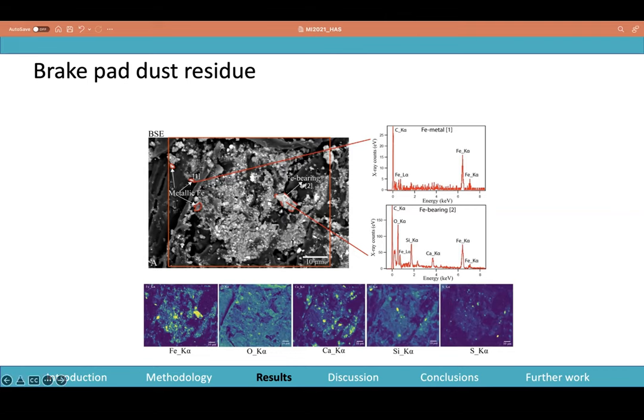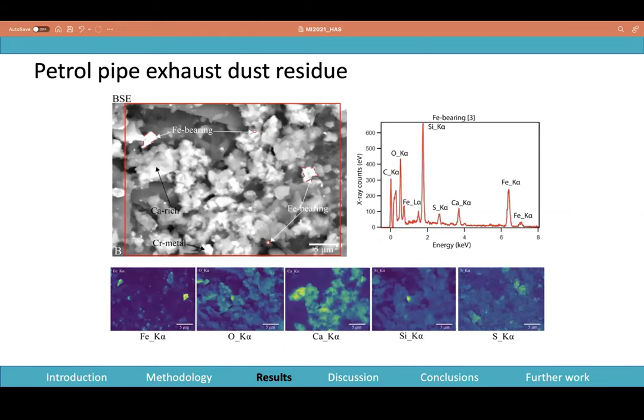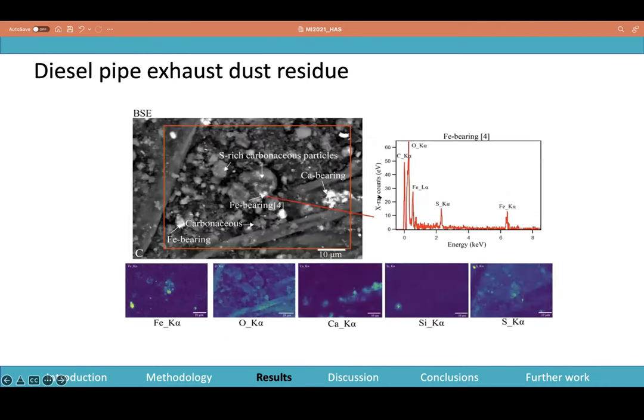This is a brake pad dust residue sample, and this shows the presence of metallic iron and also the presence of an iron bearing phase, which possibly has iron oxide, but also something which is calcium silicate. This is a petrol pipe exhaust dust residue sample, which also has this Fe bearing phase, but also something else within that. This is a diesel pipe exhaust dust residue. You can see there's iron sulfate, or some form of maybe very magnetic iron sulfide phase present in these particles.